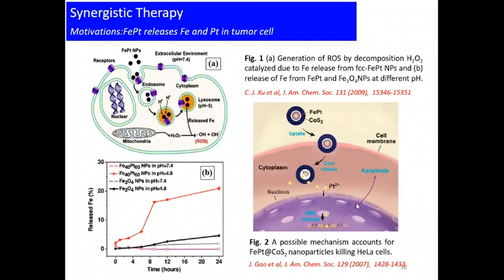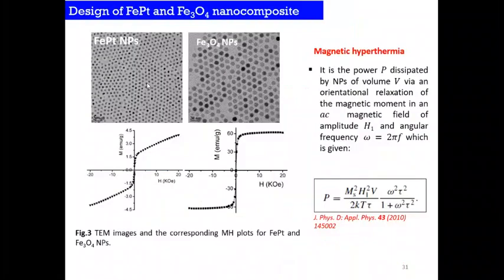So as we work on the iron platinum, one of the disadvantages is that it possesses very low magnetization. If you see, the magnetization is 3.5 emu per gram, which is not useful for power dissipation. It cannot generate the heat. So why can it not be combined with the iron oxides? We have checked that in iron oxide the magnetization is quite high. So if we make a composite of iron platinum and iron oxides, this can be used for combination therapy.